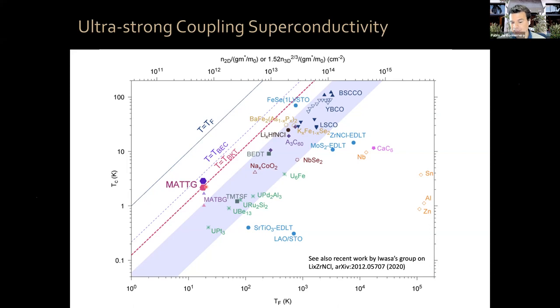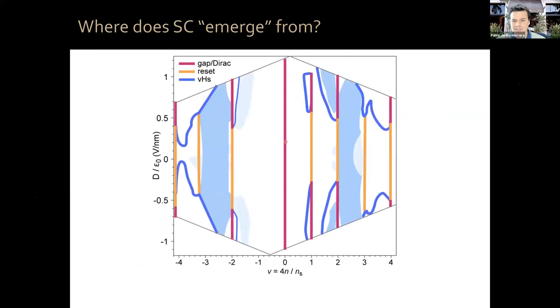Typically we measure superconductor strength by comparing critical temperature versus Fermi temperature. Conventional superconductors tend to be in one corner; the cuprates, nitrides, heavy fermions, and organics are more exotic. Magic angle twisted trilayer graphene data points are at the BCS-to-BEC crossover lines, making it the strongest-coupled superconductor that exists. If the cuprates had the same coupling strength, they would be well above room temperature. There is a second system — indium doped SrTiO₃ or possibly (Li,Fe)OHFeSe — which also realizes this ultra-strong coupling regime.